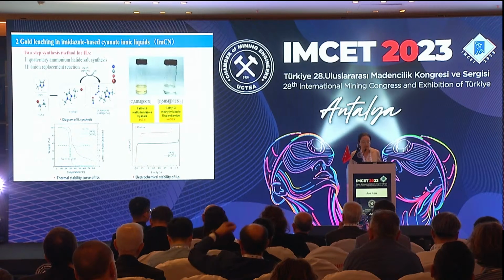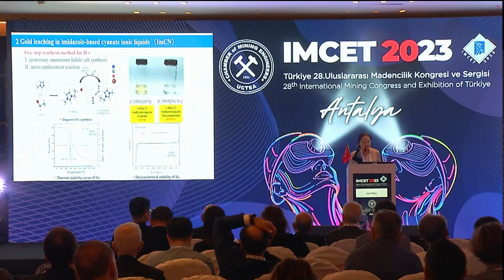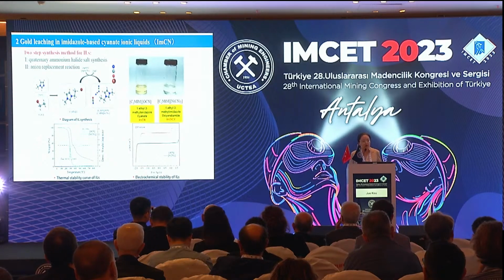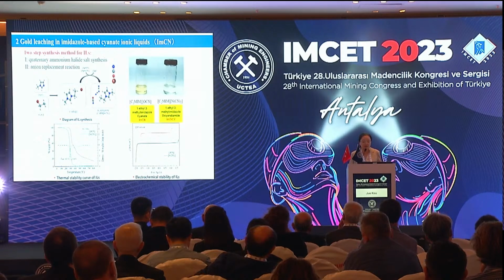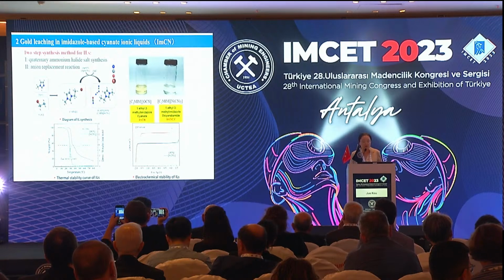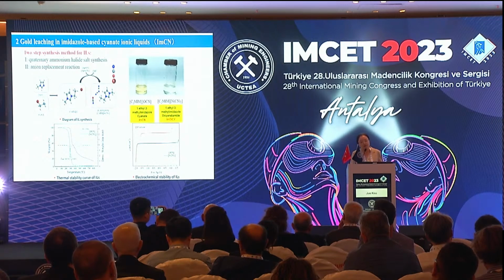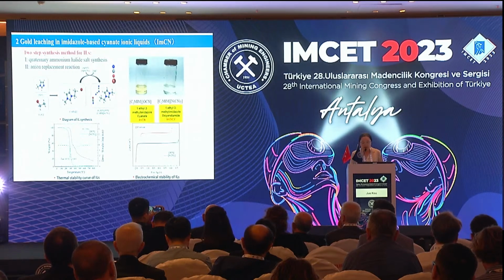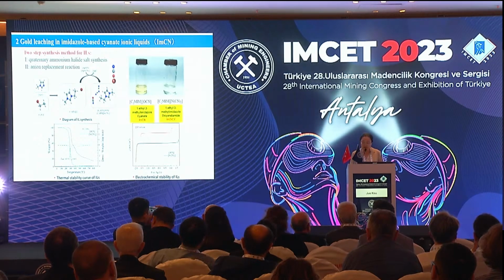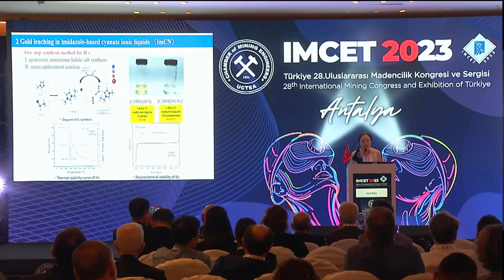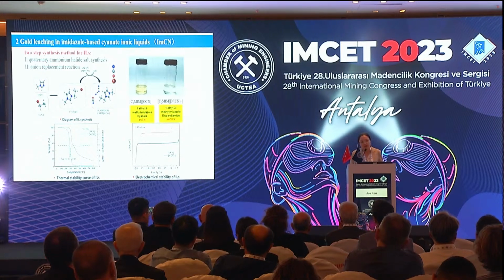And it turns out that these 2 products have very good thermal stability below the temperature of 100 degrees Celsius, which is quite good because in most gold leaching processes the temperature is not higher than 100 degrees Celsius. Therefore, we can adjust the temperature to the degree that is suitable for the gold leaching without changing the chemical property of the solvent. And for electrochemical stability, we've tested the electrochemical window of these 2 products, and they all show a very wide window, which proves the stability of these 2 ionic liquids.